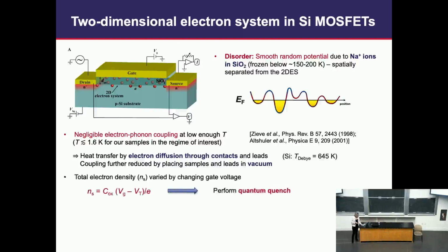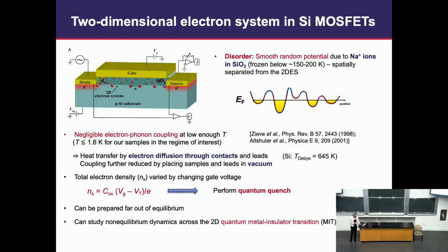So as I said, we can perform this quantum quench protocol. We can instantaneously change the carrier density by a large amount, taking the system very far from equilibrium. We can also perform these measurements systematically for different densities, starting from the high density regime where the system is metallic, and moving to lower densities where it becomes insulating. Finally, this is what we did: we looked at these devices.